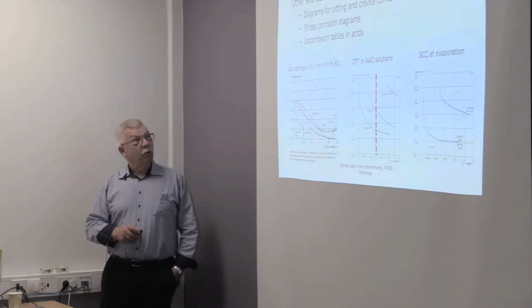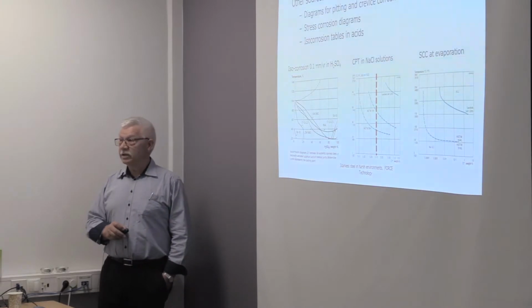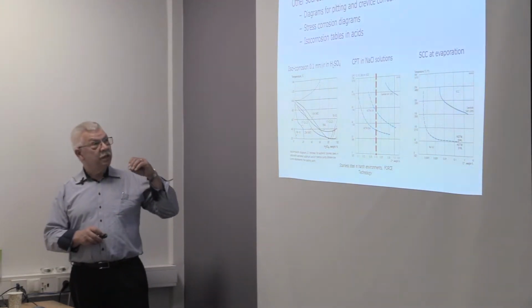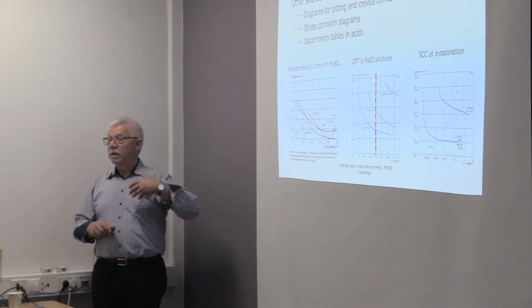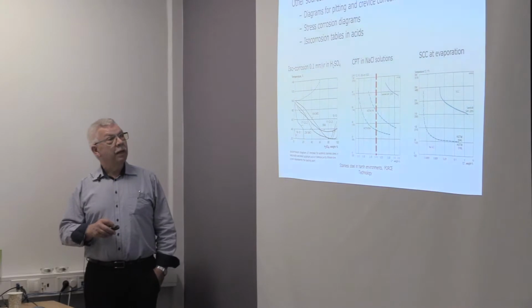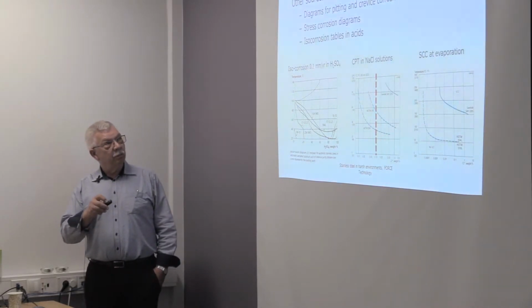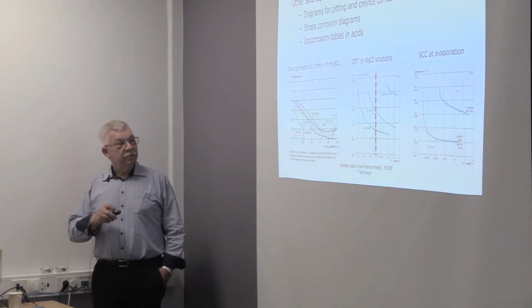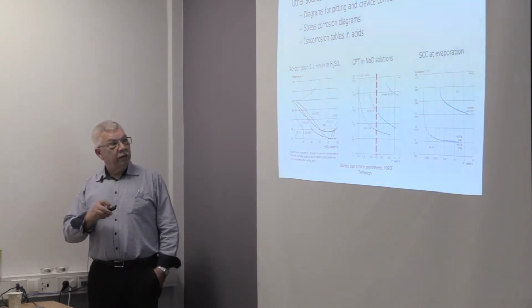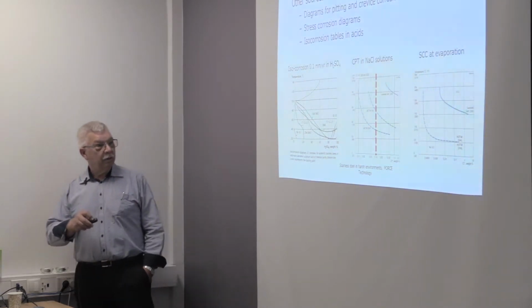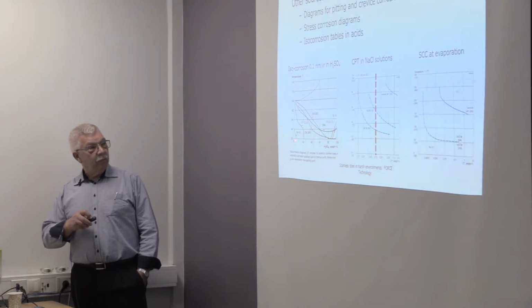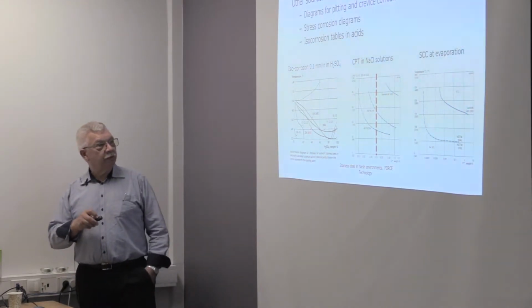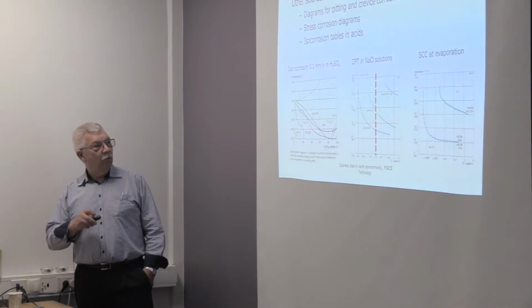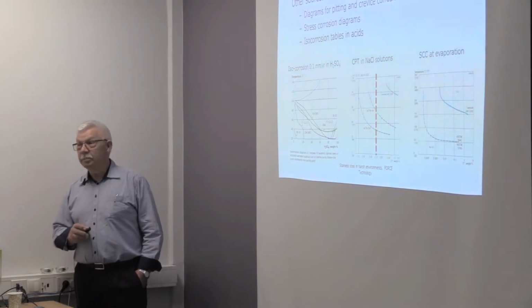We also have something called iso-corrosion diagrams. That applies for acids, where we have general corrosion, where the passive layer is continuously dissolved in the solution. And in that we can have lines which say 0.1 millimeter per year, and we can select a material which will be below this line for a certain amount of sulfuric acid in this diagram. And we can see that if we go to 40% of sulfuric acid, then this 254 SMO will not go above 40 degrees C before it hits the 0.1 millimeter per year.